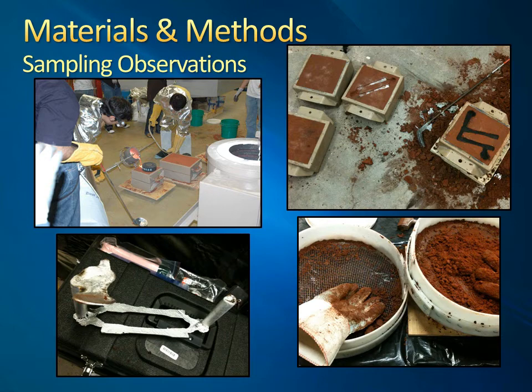The finishing step of grinding and polishing was never actually performed. The castings are used mostly to teach casting techniques and to show metal stresses under high temperature, so no finished castings were ever actually produced. The castings, once cooled, were washed in water and were only given a quick polish with fine grit sandpaper by hand. The physical processes that would have broken down larger silica crystals were not seen.